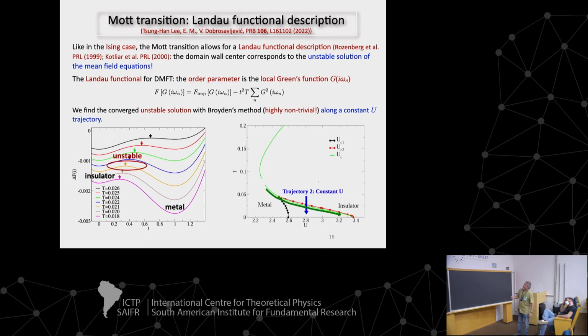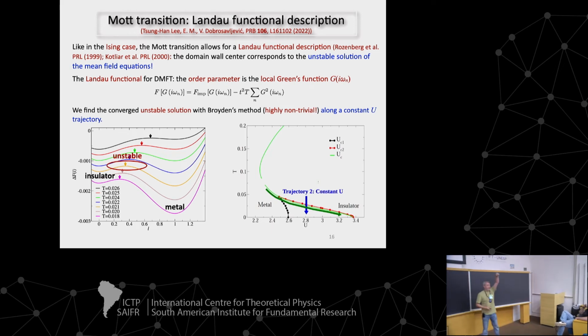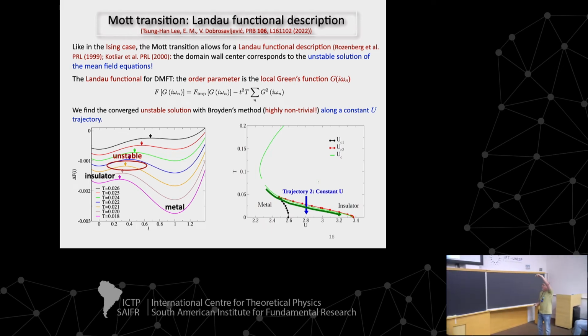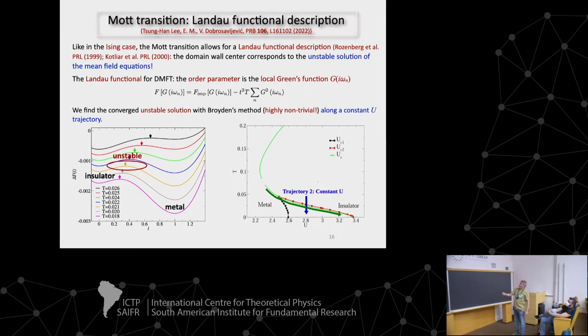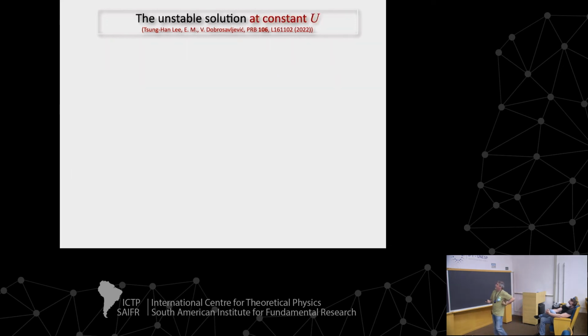So we can construct the free energy, and you can see that there are two minima, insulator and metal, and you can focus on the unstable point. I'm going to show the behavior of that unstable point once again. Actually, in this case, I'm going to go on a vertical trajectory. In other words, fixed U, and I lower the temperature as I cross the phase transition from the insulator to the metal, or the other way around.